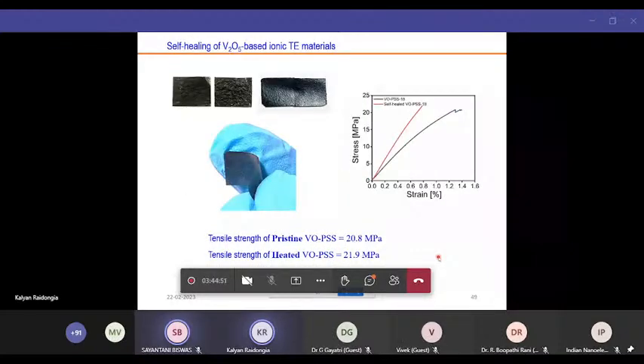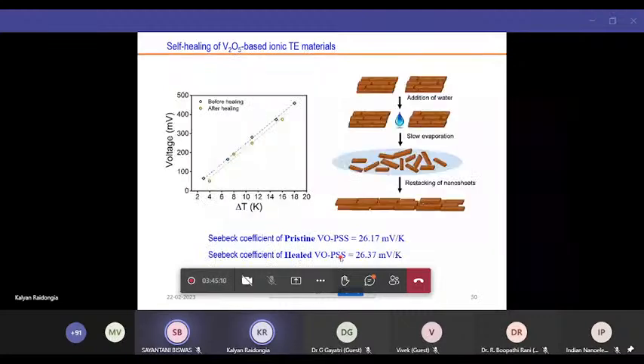Similarly, this material also has very good self-healing characteristics. You can cut it into pieces, and you can put them together with a small amount of liquid. Then again, you can see the structure is regained and its mechanical properties are also regained. And with this regained structure, you can cut and damage it and heal it again, not showing any degradation in the thermopower.